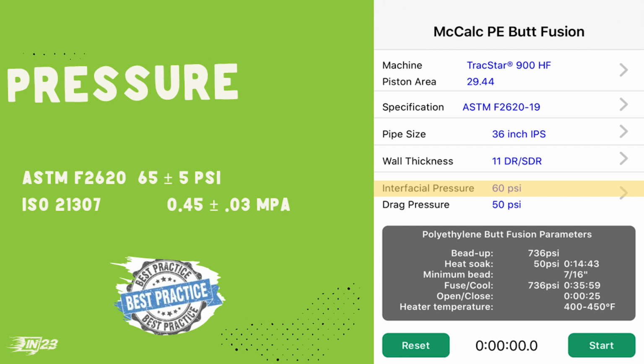And then, again, up here, what he's got is 65, plus or minus 5. If you run right on 60, then you're down to the measurement category of the piece. So typically I see people doing 65, and that gives you a little bit of variance on how it gets dialed in and how it's measured, and if there's any chatter, you're not bouncing out of that 60 range. Awesome. Thank you for the question.